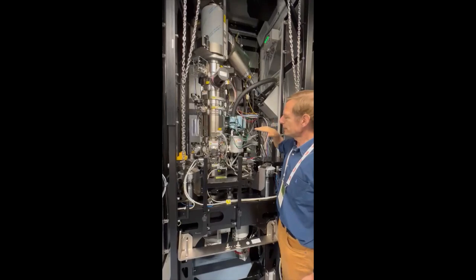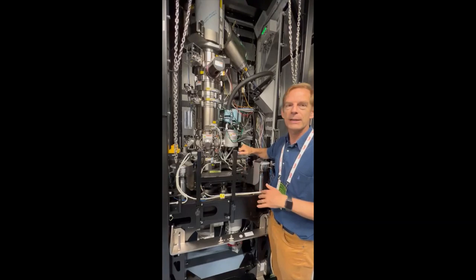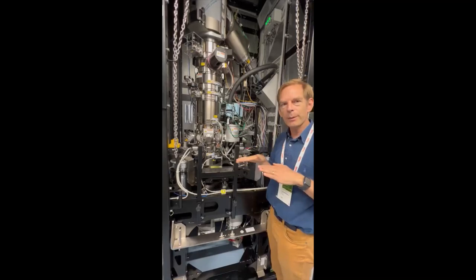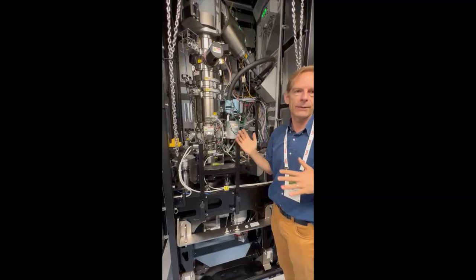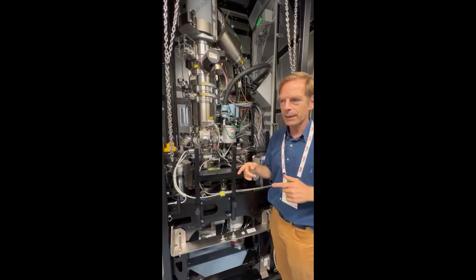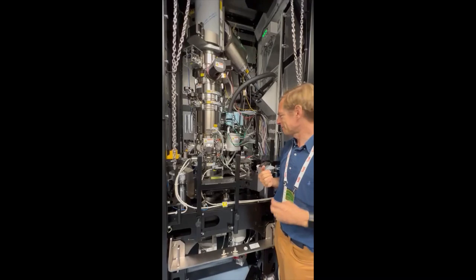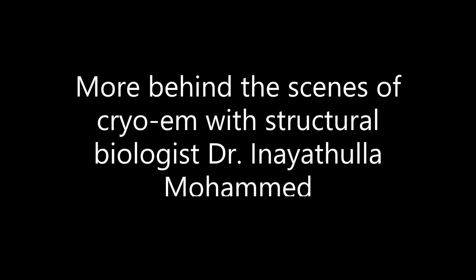We can take pictures that are so sharp that we can see atoms. The exposure time is typically one second, and the microscope is so stable that over a second it does not move by more than an atom. It's absolutely stable when we close the door. You can focus on a single atom, or you can focus on the entire ice with all the proteins and viruses and bacteria, but the pictures are so sharp that we can, after image processing, localize atoms. That is one of the coolest things I think I've ever seen in my life.